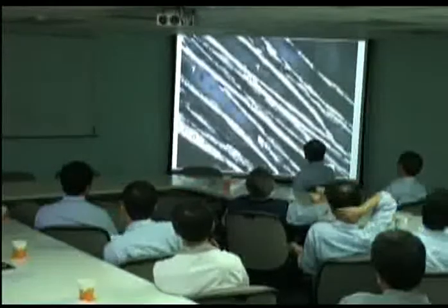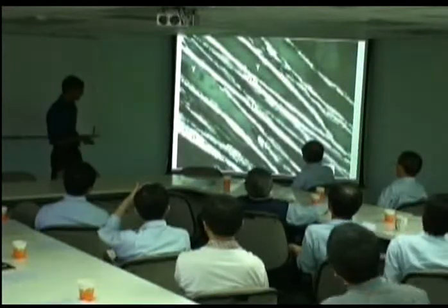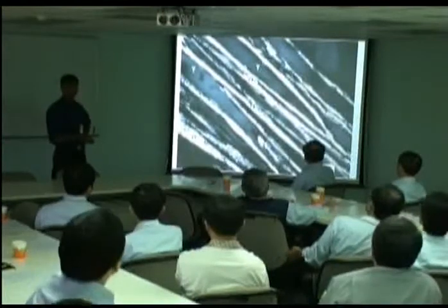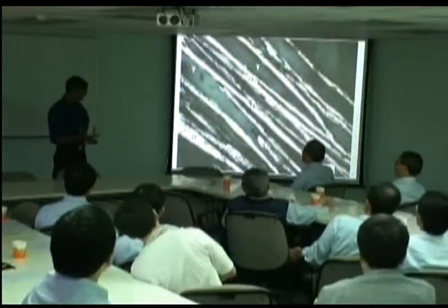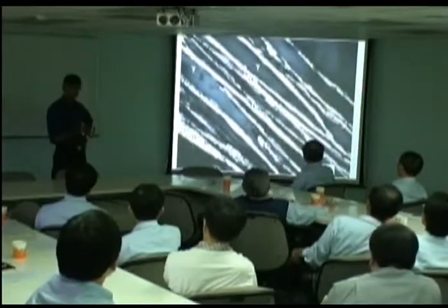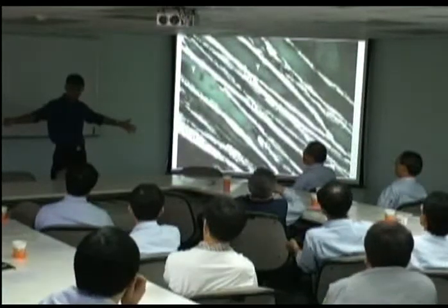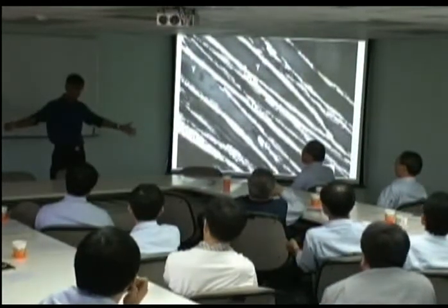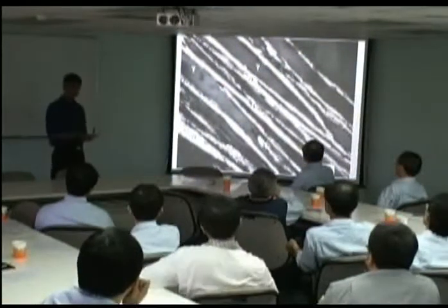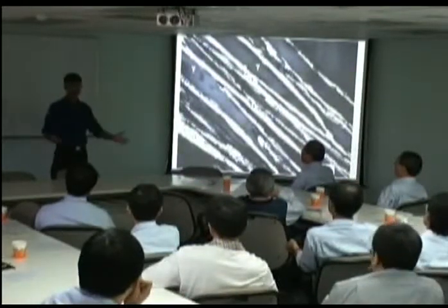This is an absolutely spectacular image. I want you to look at the scale here. If you can't see it, please get up because it's very important. It's 20 nanometers thickness here. These are plates of bainite produced at 125 degrees centigrade. Large sample of steel, no rapid cooling, no deformation, we naturally produce a grain size of 20 nanometers, extremely cheap. What more can you ask for?